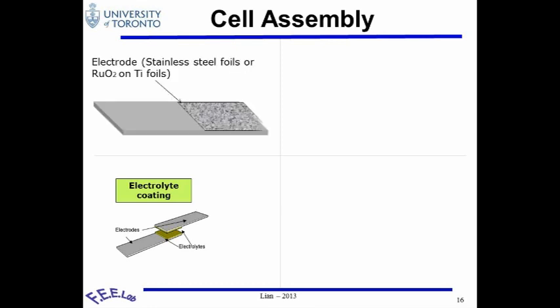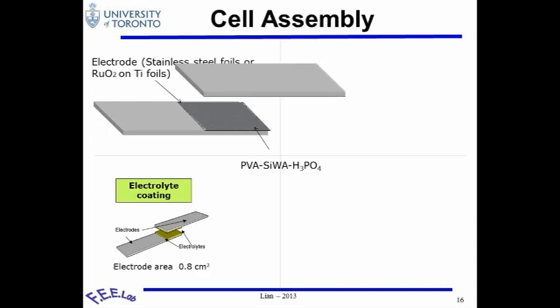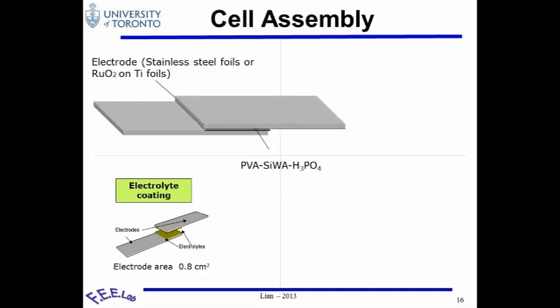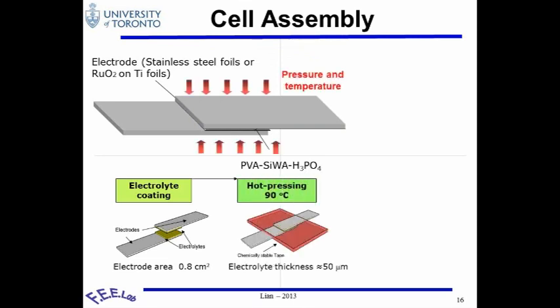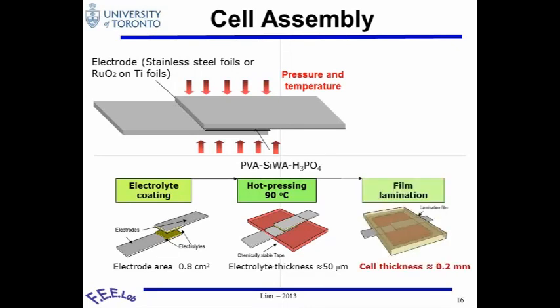Our cell assembly started with a very simple 2-electrode setup, with thin foil metal current collectors made of stainless steel or titanium, onto which we coat different kinds of active material to make the electrode. We apply the film by painting, coating, or sandwiching, then laminate the other similar electrode, making it a symmetrical device, pressing them together with pressure and temperature.